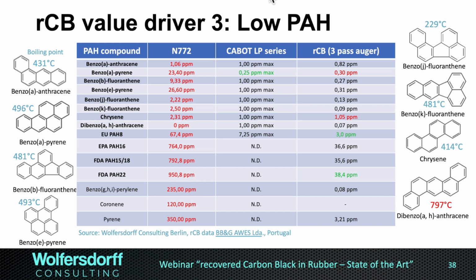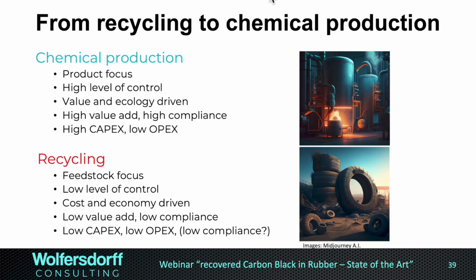Third driver, low PAH. There are specific low PAH furnace carbon blacks which are much more expensive than the ASTM grades, and recovered carbon black delivers that if the pyrolysis has finished, if the pyrolysis was sufficiently long and hot. We have a low content of PAH, which might actually also qualify you for food contact, but that is an entirely different topic. And so now we're really talking about a chemical production, delivering a sustainable material, delivering a low carbon footprint, delivering low PAH. So we're talking about a product focus, and this is the paradigm change.